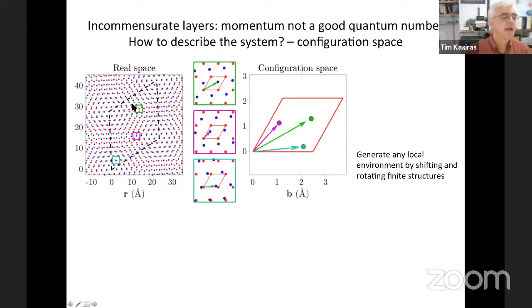So the dashed black lines outline the Moire supercell, and you see different types of local configurations here. Here are blow-ups of these local configurations. If you refer everything back to one of the lattices, let's say the red lattice, then you see different positions of the second lattice shown by the different colored arrows here. And from these local arrangements, you can generate any local environment simply by shifting and rotating finite structures.